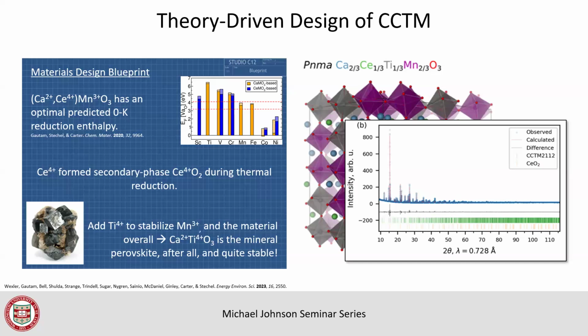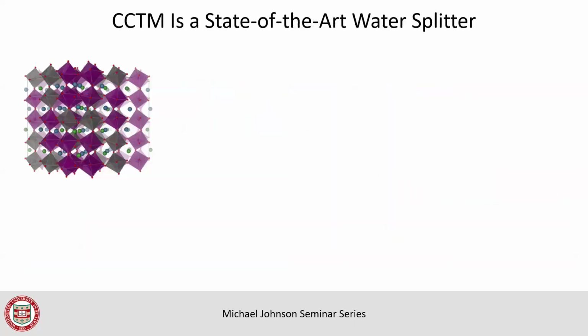Basically this plot on the right here is the result of just scattering a bunch of X-rays off a material. What's really neat about it is, based on the X-rays that bounce off, you can process that and reconstitute where the atoms were in the crystal. We can compare that against our crystal. It matches almost perfectly. It's tough to see, but if you track the blue data points and the red curve, blue is experiment, red is theory, or what we predicted, it matches almost perfectly. So number one, it can be made.